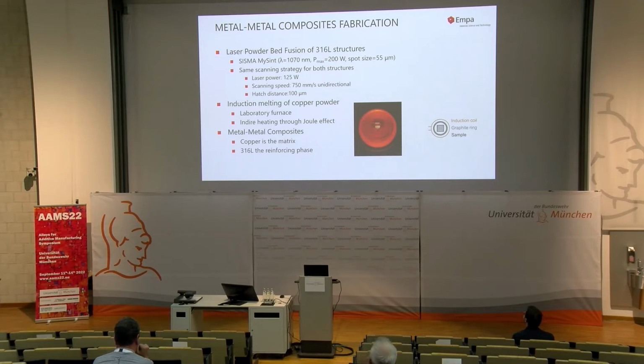Then we use induction melting. We have a laboratory-based furnace at EMPA in Dubendorf. And what we do is that we put the sample inside a graphite mold, which is surrounded by the induction coil. So we play with the creation of alternating electrical and magnetic field within the sample, and we will end up heating the copper powder through the Joule effect.